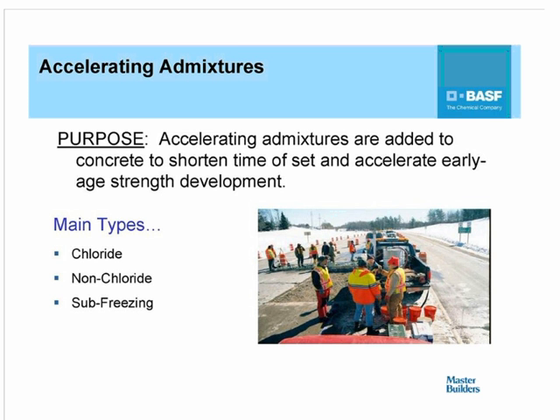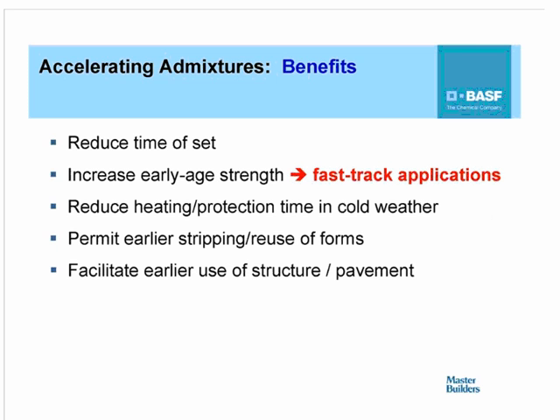Now, accelerating admixtures, on the other hand, are used to do the exact opposite. When the weather cools down, accelerators are added to concrete to shorten the time of set and also to accelerate early age strength development. The main types are the chloride-based admixtures, which are very effective and are typically used in residential applications, non-reinforced applications. But for reinforced concrete applications, the non-chlorides exist. And within the non-chlorides, there's a subcategory that are used in sub-freezing ambient temperature environments. The main benefits are to reduce the time of set of concrete, to increase early age strength development,